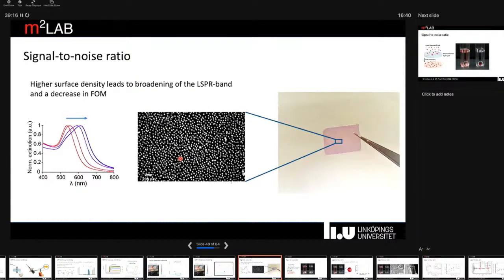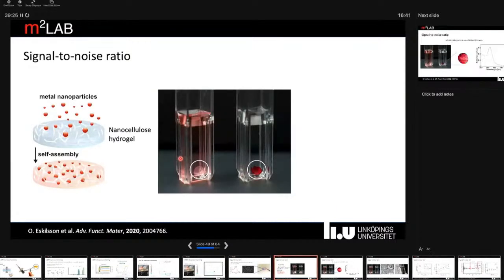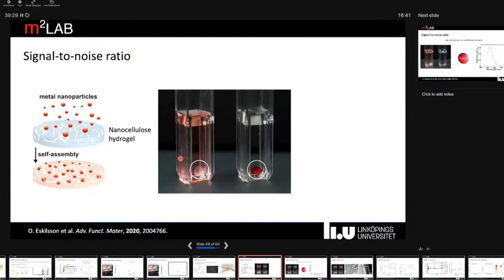So we started to look at possibilities to instead increase the number of particles in the third dimension by using three-dimensional substrates. And one such substrate that caught our attention was nanocellulose hydrogels. So these are essentially biopolymeric, water-rich materials, but can be produced with really high quality and reproducibility. And what you see here in the bottom of this cuvette is one of these cellulose membranes. And we wanted to develop an approach where we use self-assembly of particles in here, so we can start with well-defined particles. There have been a number of papers published on attempts to synthesize particles in nanocellulose, but then you don't have the same control over particle size and composition and shape as you can if you prepare particles separately and then adsorb them in the cellulose.